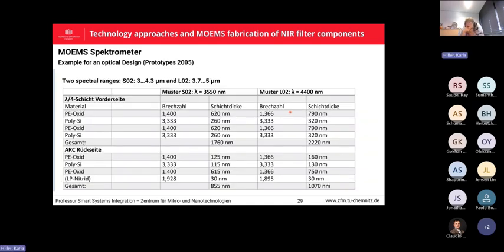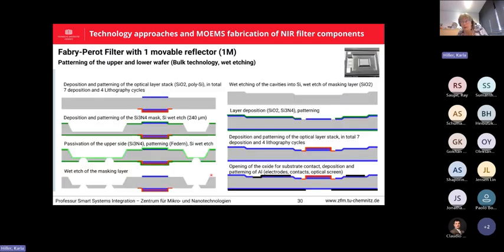So more sophisticated designs of these layer stacks are shown here for different working ranges. And also the anti-reflection coating is here much more sophisticated, not just one layer, to get the best results. Yeah, and for the technology of this approach, we start with depositing the layers. So silicon dioxide and polysilicon are thermal or CVD processes, so the layers are deposited on the whole surface.